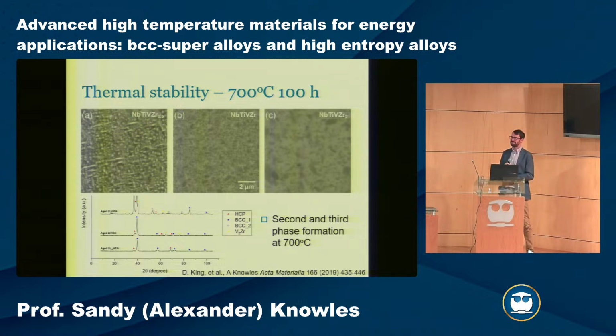You mentioned that in order to build the model to predict how a superalloy behaves, you have to do experimental work. Do you have a set of standard steps to get there with every alloy, or do you have to do something different with every material? Yeah, in theory it's a common process. We have a process that many people in the research group, and I guess Lily and you will be able to comment on, where we can arc melt a material, then do thermal heat treatments, then go into scanning electron microscopy, X-ray diffraction, and different methods where we create a base characterization. And then sometimes it doesn't work. That's the nice thing about doing discovery and experimental science: you have an idea when you go in about what will happen, but sometimes it's not perfect, and then you have to refine your idea and improve. But we try to have a common approach so that we can compare from one material to another. So if we get a strength from a given material under different given conditions, we know that it's comparable.